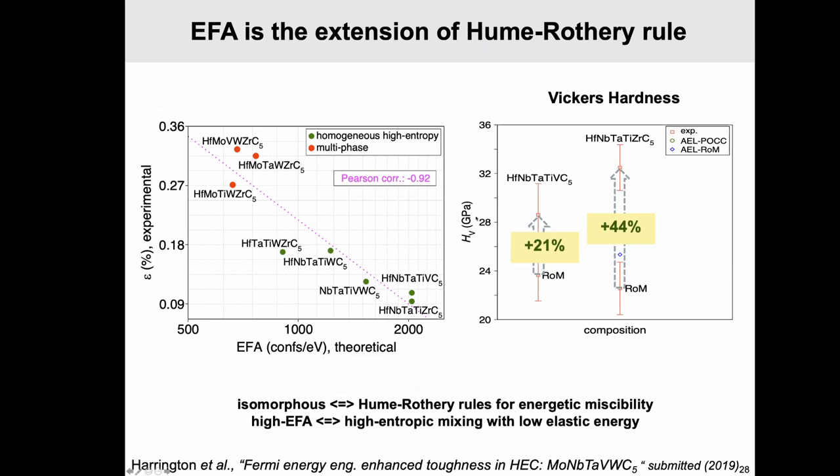But remember, what is hardness really? Hardness is resistance to indentation. So you have an indenter, nano or micro, whatever. You hit your system at a certain force, and then you check the scratch, right? The little dent that you make. Okay, this is hardness, right? The smaller the dent, the harder the material, right? Okay. So what is really hardness? It is resistance to scratch, which relates to how deformations can propagate in the system. So how dislocations move in the system. This is really a plastic property, okay?